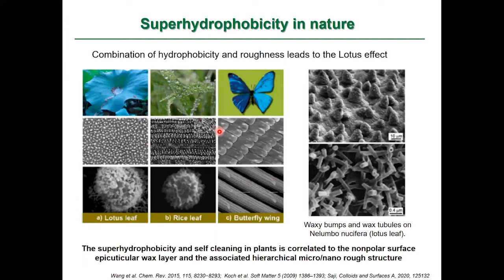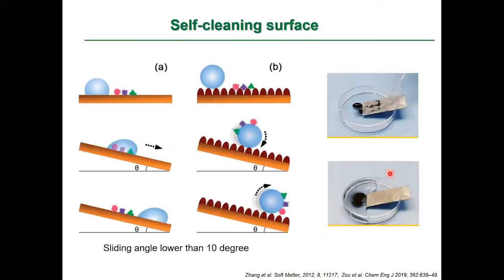See, these are the examples. You can see the waxy bumps on a lotus leaf and its nano-micro scale surface. So this is the nano-micro hierarchical surface structuring combined with the epicuticular wax layer, hydrophobic wax plus the nano-micro structuring. That is actually responsible for the superhydrophobicity in nature. So we are mimicking that. This schematic shows how a surface having hierarchical surface structuring can remove the dust and perform self-cleaning when compared to a plain surface.